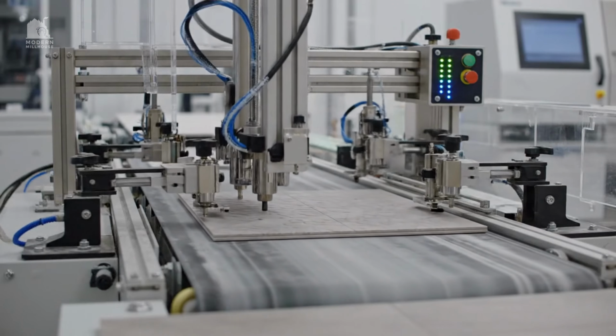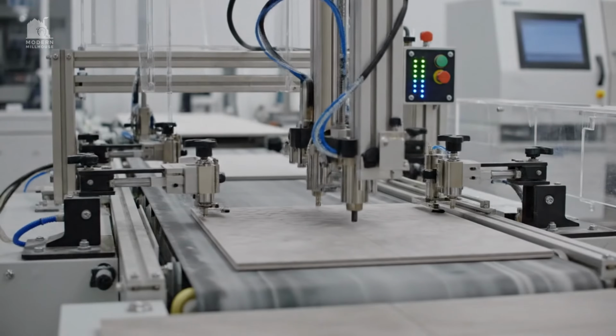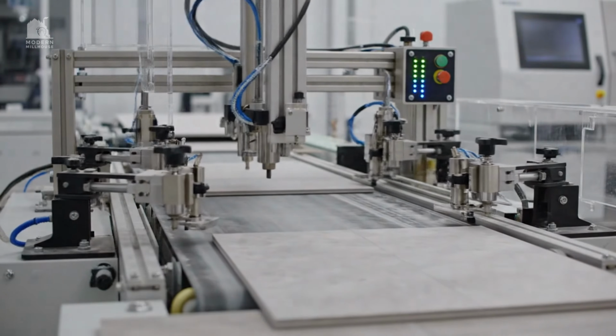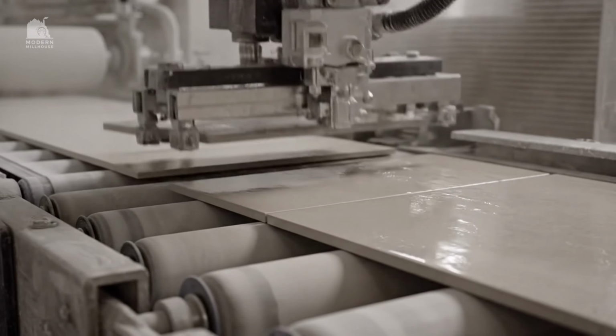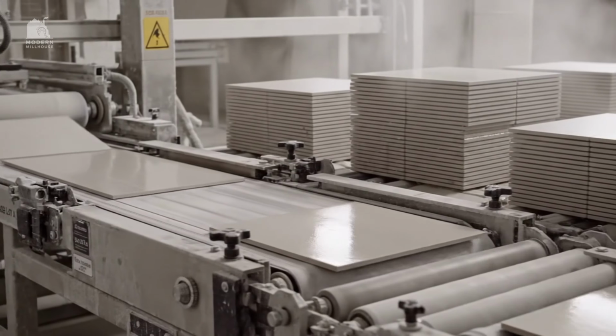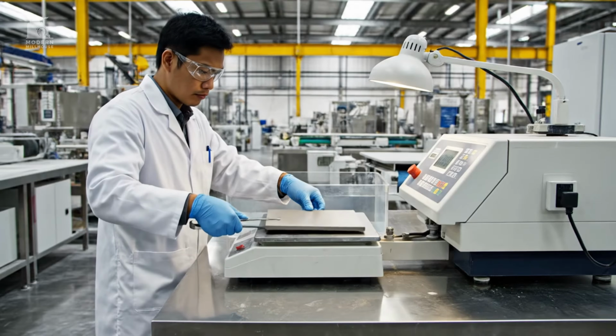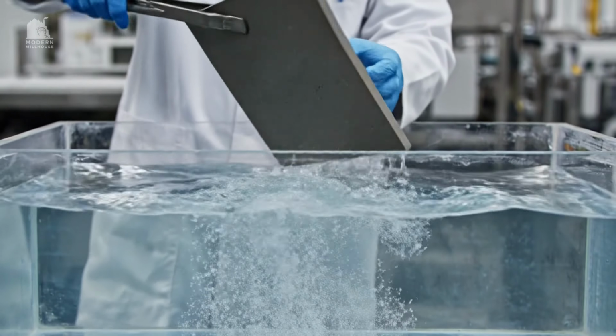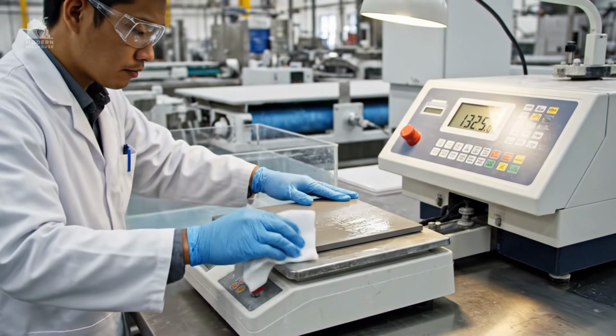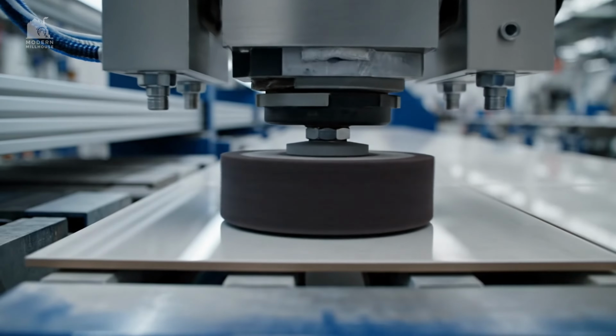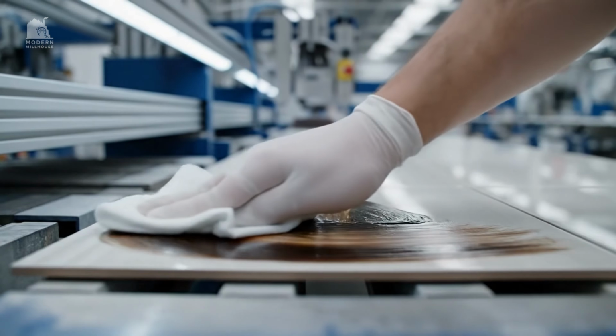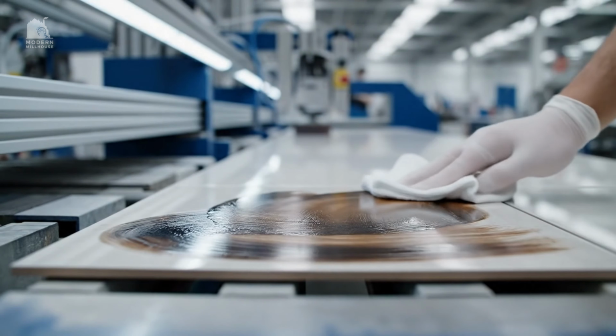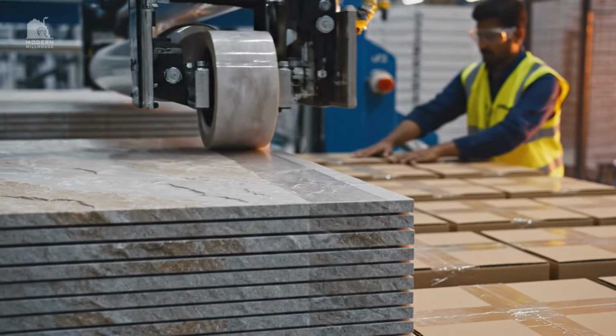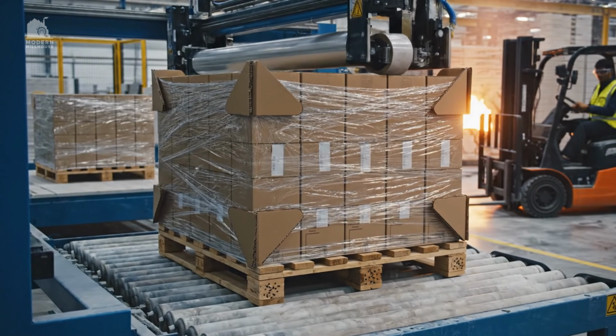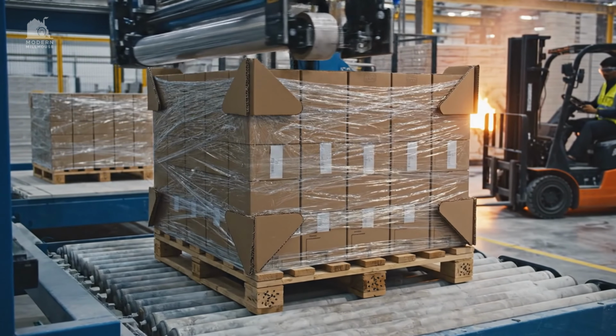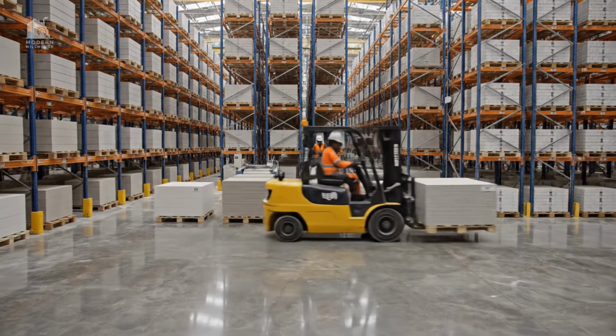Because firing shrinkage varies slightly, tiles are sorted into calibers so installers can keep joint lines consistent. Color is sorted into shade lots so a finished floor does not show patchy shifts from box to box. Plants perform property tests on samples. Water absorption testing shows how porous the body is and how suitable it is for wet environments. Breaking strength tests check integrity, while abrasion and stain tests evaluate surface durability. Slip resistance tests may be performed for products intended for wet areas, especially textured finishes. Tiles that fail can be downgraded or discarded.